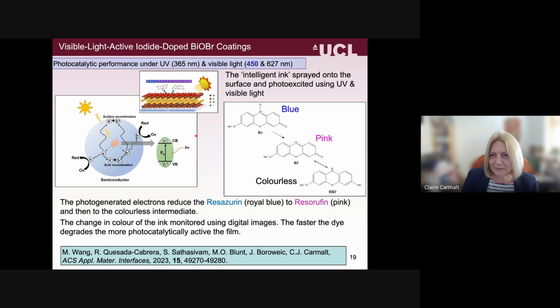So when we've made it, we then test the photocatalysis, and we use something known as an intelligent ink. We spray that onto the surface, and then we photoexcite using UV and visible light. You start with this compound, which is known as resazurin, which is blue, and the photo-generated electrons reduce the resazurin down to this pink intermediate, and then it can go all the way to this colourless intermediate. And the change in colour of the ink is monitored using digital images, and the faster the dye degrades, the more photocatalytically active the film is.